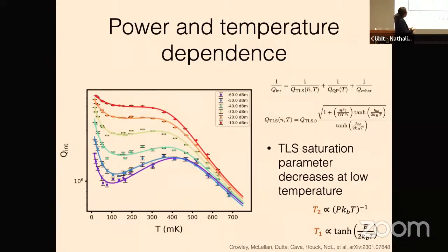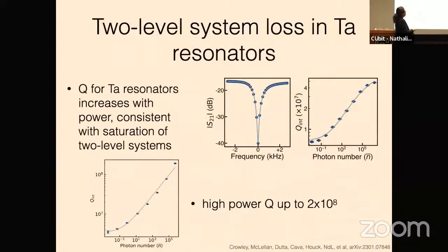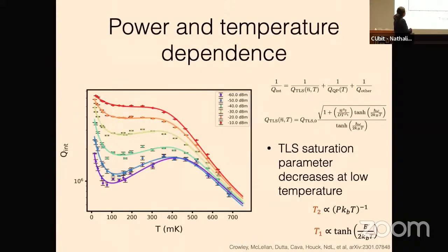Okay, so this is a power dependent curve. And we can take this one step further and do a temperature dependence of the power dependence. So basically, each vertical slice is one of these power dependencies. And then we just do one of these power dependencies at many, many different temperatures. And then what we can do is just take our loss model seriously and try to fit all of